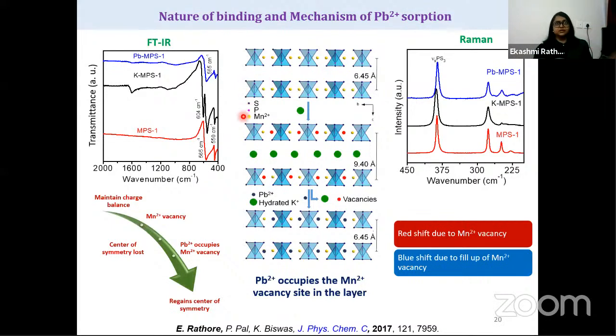Now, let's look at how this binding happens and what the mechanism behind the lead sorption is. Here this is the MnPS3 structure, and the green one is potassium. When we introduce excess positive charge into the system, Mn2+ goes out to maintain charge neutrality. Now when we treat our samples with lead nitrate, the lead goes to the vacancy sites created by manganese. This is the mechanism, and we found it out using IR spectroscopy and Raman spectroscopy. So till now I discussed the qualitative analysis.